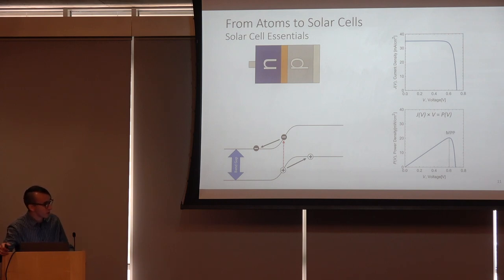From the power density, we're able to very quickly extract what the maximum power is, so the optimal voltage at which we should be operating our solar cell. So then going back up to the top diagram, the X and Y intercepts are the open circuit voltage and short circuit current, respectively, highlighted in the green there. And they're basically measures of the maximum voltage and current that your solar cell can ever really produce when it's in the power producing quadrant of your JV curve.